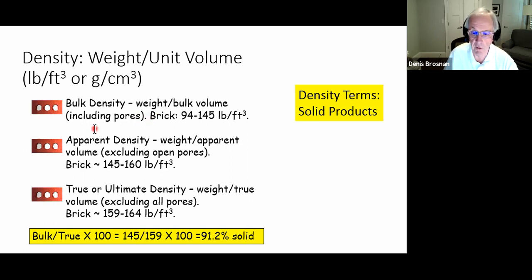Then there's the apparent density, the weight divided by the apparent volume. That means they're excluding the open pores. So that would include the weight divided by the volume, excluding any open pores that we can penetrate. That gives you a little bit of analysis capability, because you can compare apparent density to what's called the true density, and you can figure out how close you are to fully densifying the ceramic. Of course, the true density, sometimes called the ultimate density in today's world, is the weight divided by the volume excluding all pores.